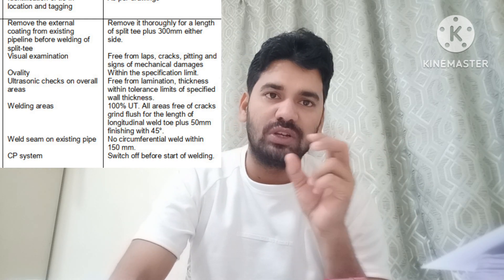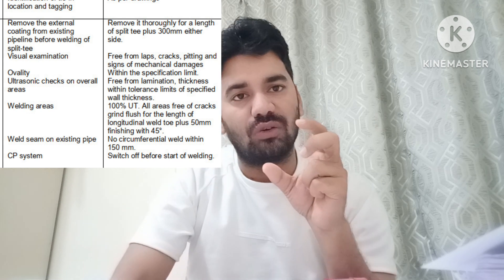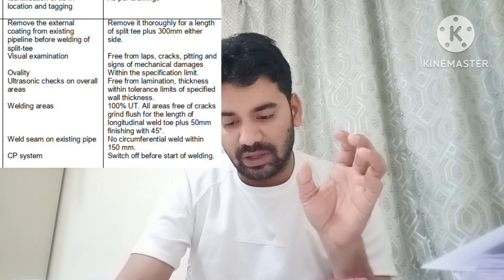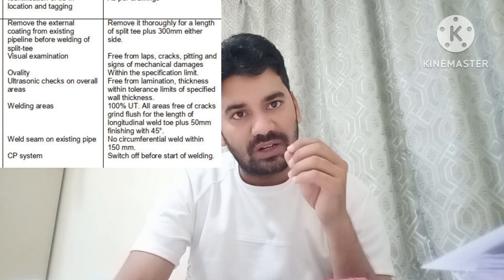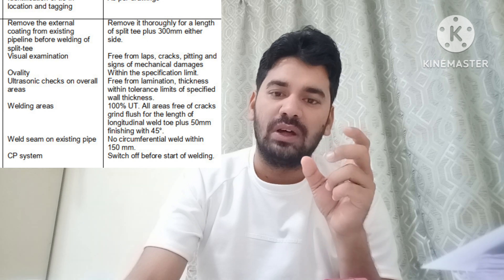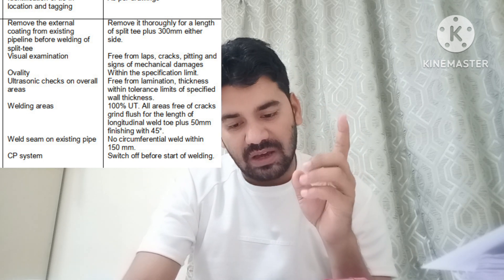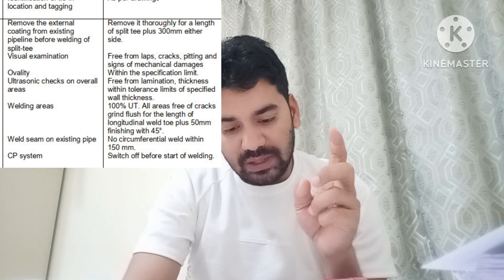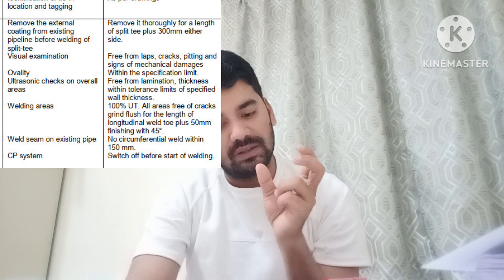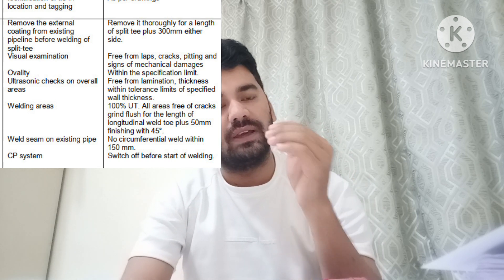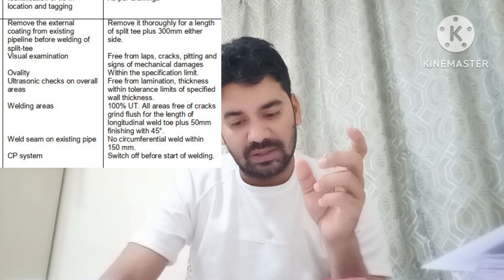Next is ultrasonic testing of the overall area. When working on a pipeline, UT is done to check that the area is free from lamination and that wall thickness is within the tolerance limit per the specification. Wall thickness is especially checked in the welding area — 100% UT of the welding area. That entire area must be free from cracks. Grind the full length of the longitudinal weld plus 50 mm, covering the longitudinal and circumferential welding areas.